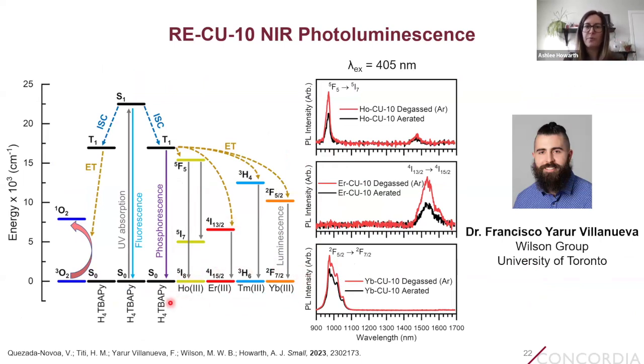And in order to probe that, we wanted to look at the near-IR photoluminescence, basically to see if we excite into the pyrene at 405 nanometers, do we observe near-IR photoluminescence from these 4 lanthanides? Because if we do, then that shows that the energy transfer is taking place, and that energy transfer could be a competitive pathway with the generation of singlet oxygen.